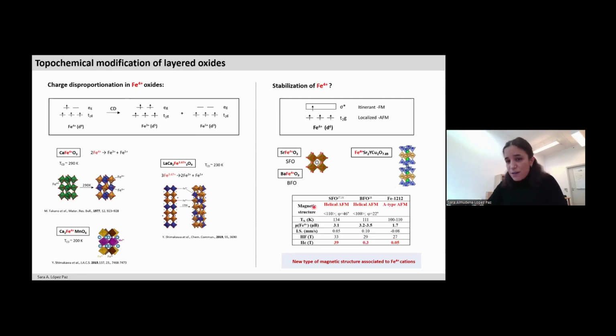If we manage to have a structure that is not too distorted, so that we can have extended enough covalency, we can actually make these electrons participate in itinerant bands, and in this way retain the nominal iron 4+ oxidation state down to base temperature. And these materials are even magnetic. In the literature, we could find only 2 examples of this, while our compound was then a third example so far of magnetic properties of iron 4+ oxides.